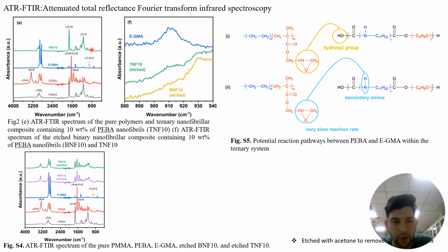So to address this issue and identify where the peak is, in the ternary system we remove PMMA from the composite. We etch PMMA with acetone to see where this peak is and what it is doing. So let's look here to figure out the issue.